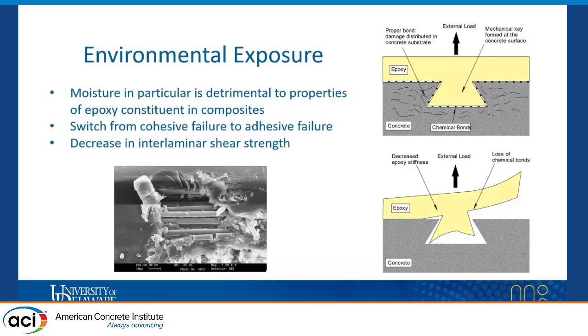When epoxy is exposed to moisture, it loses its stiffness and it also softens. Because of this, we see a loss of adhesion and mechanical interlock between the concrete substrate and the epoxy, which leads to debonding. In addition, moisture exposure to epoxy also results in a decrease in the fiber matrix interface, as well as a decrease in interlaminar shear strength.